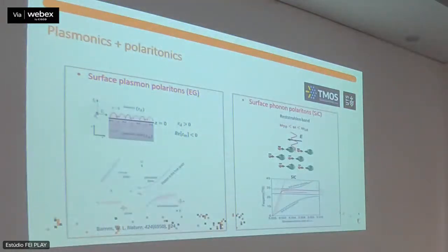And also very, very quickly, I won't spend too much time here, but what I wanted to mention is that what we can use is silicon carbide, which, first of all, is a polar dielectric. And what happens is that in this reststrahlen band, which is in the mid-infrared, the material behaves as a metal. And so it can support a surface phonon. It's not a plasmon, a surface phonon. It's just a vibration of silicon and carbon at that specific band.